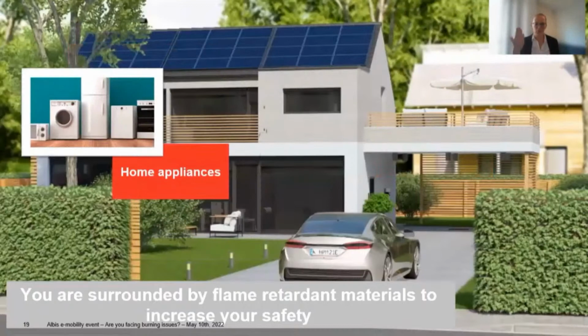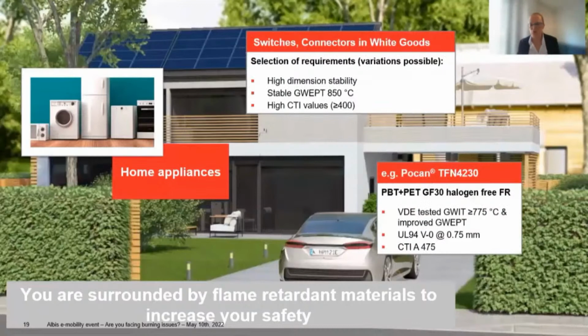And finally, maybe looking more at the E&E world, looking at your home appliances, for example, your washing machine, your dishwasher, or similar. Here, you often have a lot of switches or connectors within these home appliances, and they have to show very good dimensional stability, good tracking resistance, and a very stable glow wire performance. And especially for this glow wire performance, we have developed a Pocan TFN4230, which is a PBT PET blend with 30% glass fibers and a halogen-free flame retardant system. And this material is VDE tested regarding the glow wire index and shows very good glow wire resistance. At the same time, being flame retardant and showing a good tracking resistance.